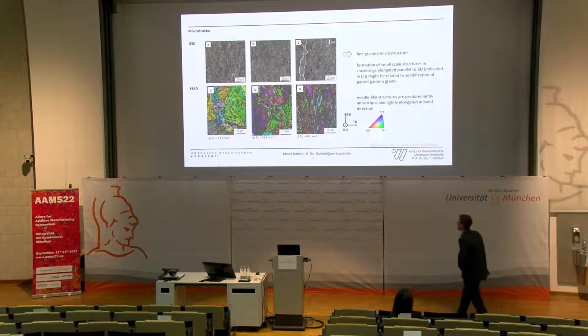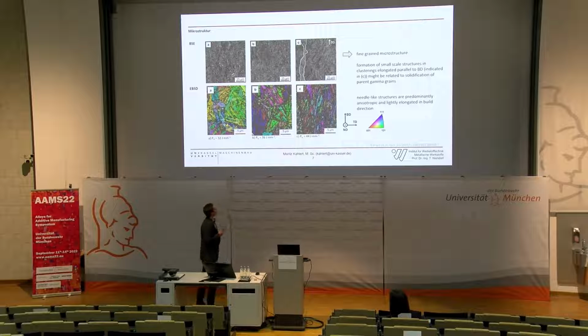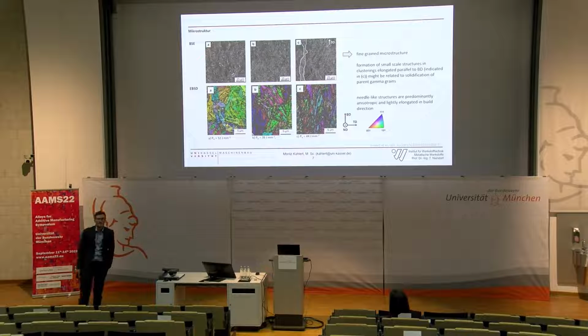Coming to the microstructure, we can see a fine-grained microstructure and a formation of a small-scale structure which is elongated and clustered parallel to the building direction, indicated in C, and might be related to the solidification of the prior gamma grains. When we look at the EBSD images, we can see a fine needle-like microstructure which is predominantly anisotropic and slightly elongated in the build direction.